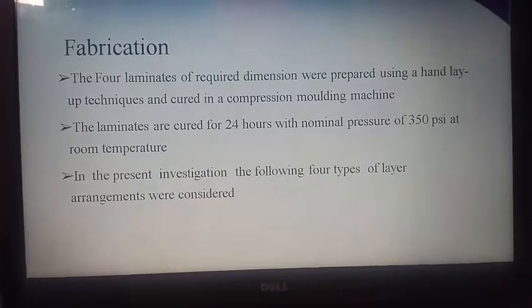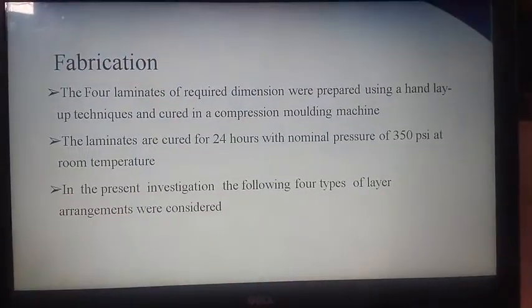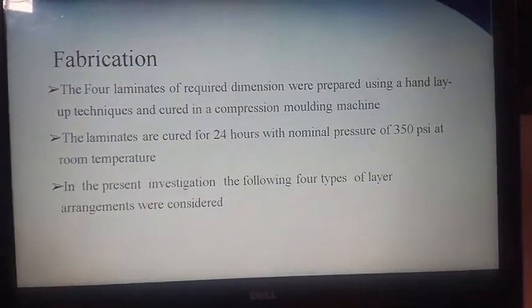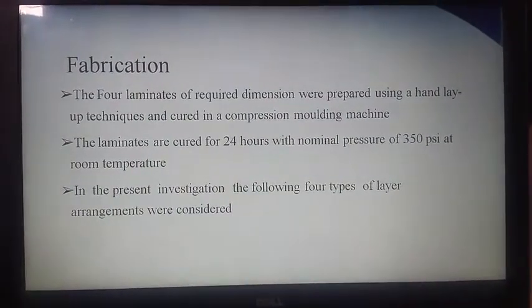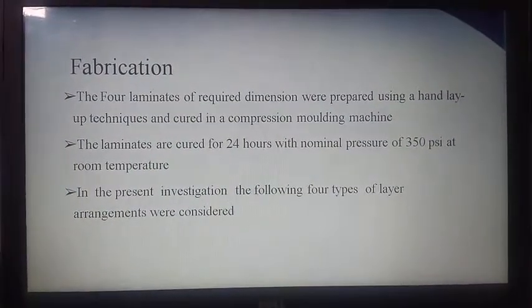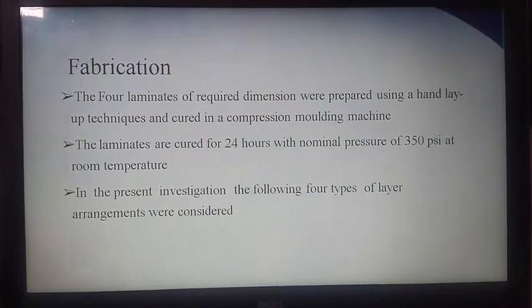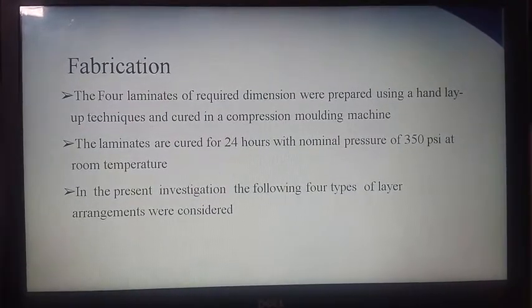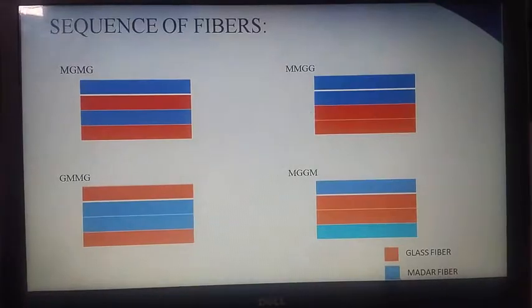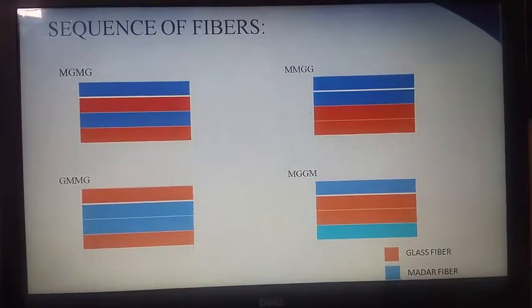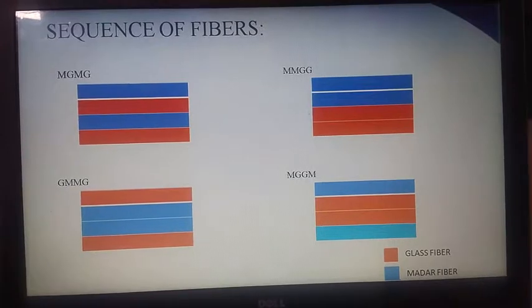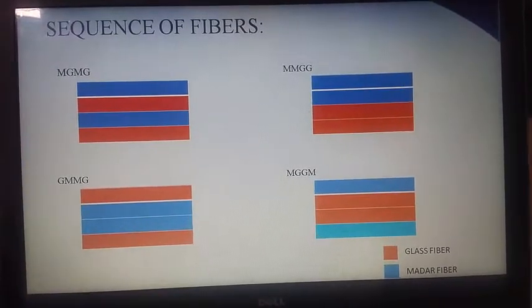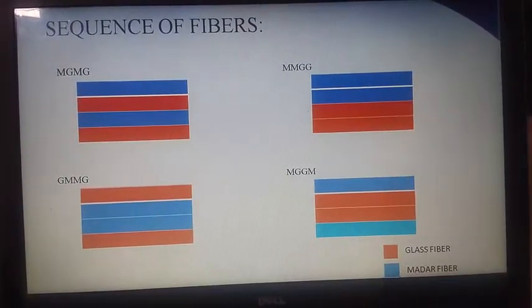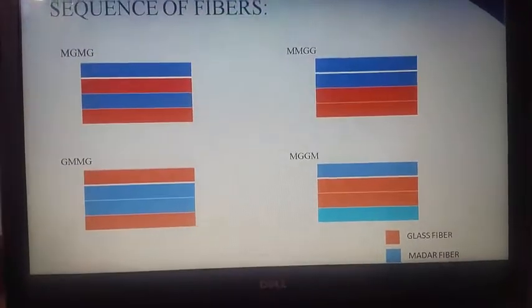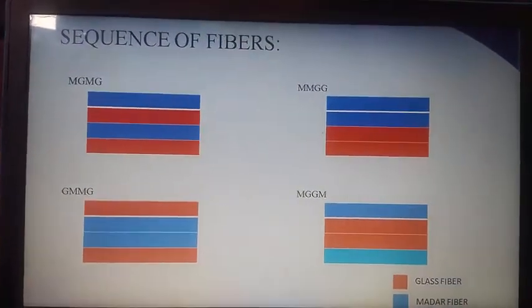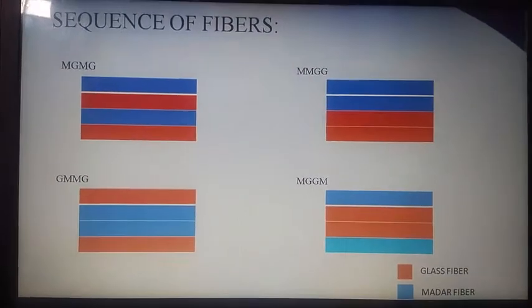For fabrication, we use the hand layup method. It's a molding method, and we use a curing time of 24 hours at 350 pounds per square inch. Actually, we made 4 sequences of the materials: Madar, glass, Madar, glass; Madar, Madar, glass, glass; glass, Madar, Madar, glass; Madar, glass, glass, Madar. We differentiated the properties of these and studied which is better and which is least.